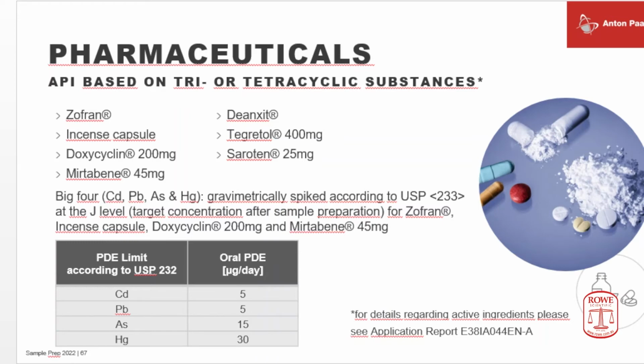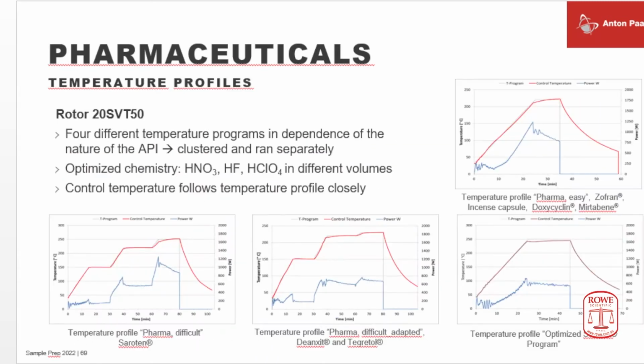We developed 4 different methods for our customers in the pharmaceutical industry. You see, like explained before, a 3-step method or a quick 1-step method, depending on the nature of the actual sample material. In this case, we optimized directly to the sample material, and also we optimized the chemistry. So it was mainly nitric, sometimes a little portion of hydrofluoric.